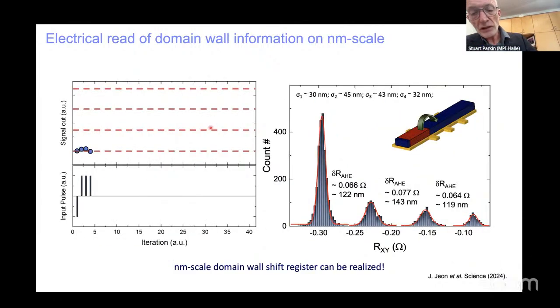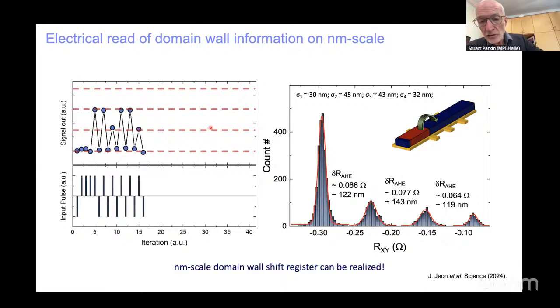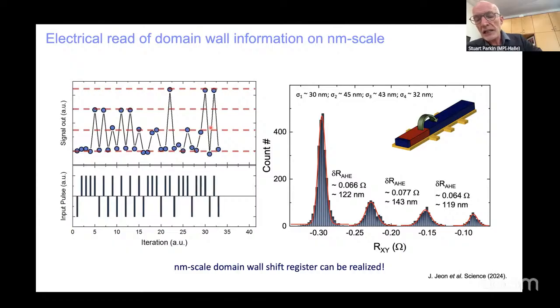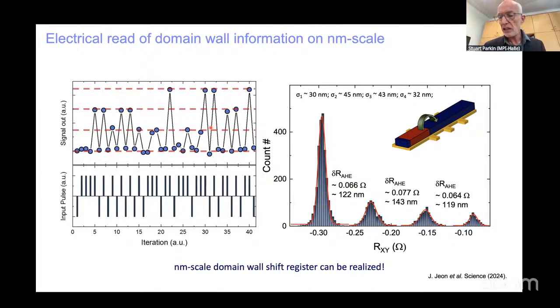And we could also demonstrate that we could position domain walls with great accuracy, to within an inaccuracy of a few tens of nanometers. Here are 4 distinct positions of a domain wall along this racetrack. And we could position two domain walls so that they're only 100 nanometers apart. These dimensions are basically the dimensions that are needed to make a technologically relevant racetrack. So we think today we've come to the point, since we started 20 years ago, that we can now build a racetrack that is technologically relevant and shows great promise.